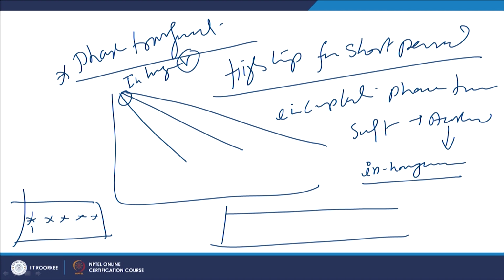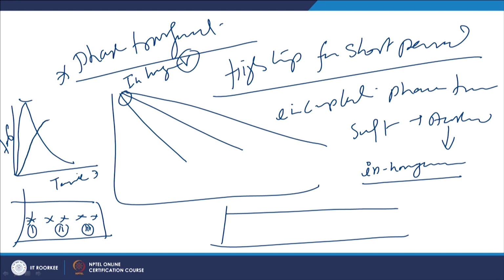If we just take the example of point 1, point 2 and point 3, the weld thermal cycle for point 1 will go like this, where very high cooling rate is observed and a higher peak temperature as far as the weld thermal cycle is concerned, time and temperature. On the other hand, for point 2, that takes longer to reach the peak temperature and then lower cooling rate, and further for point 3, a lower peak temperature, longer time to reach the peak temperature, and then a further lower cooling rate.